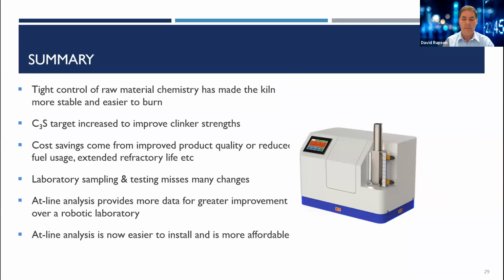So in summary, this case study has shown that using at-line analysis of raw meal for mix control will stabilize the kiln and the clinker will be easier to burn. With the more stable kiln, the plant chose to increase its C3S target to increase early strengths, something that they were never able to do before.